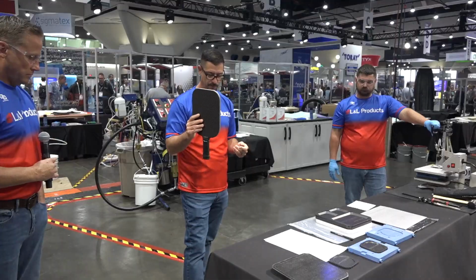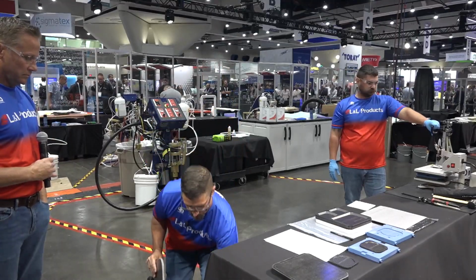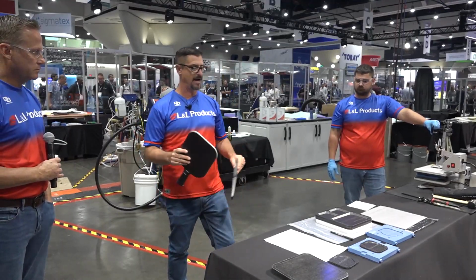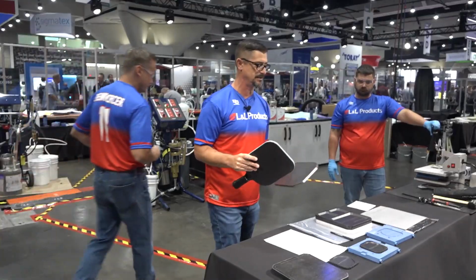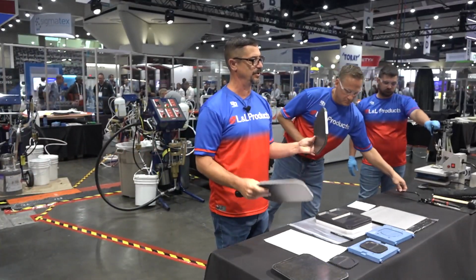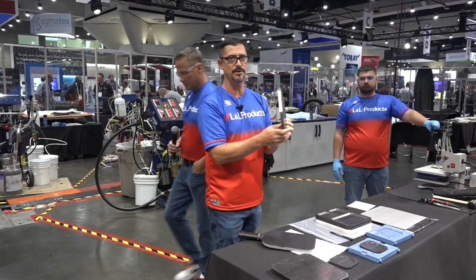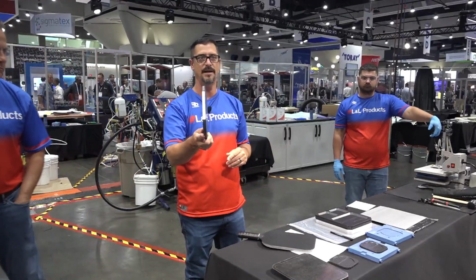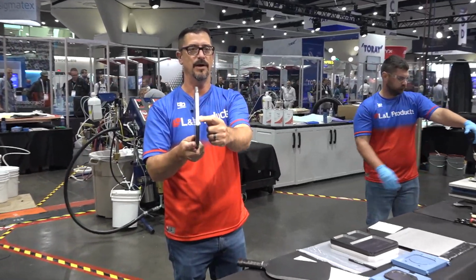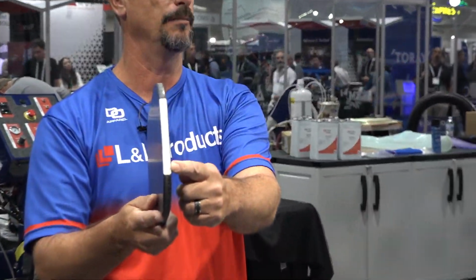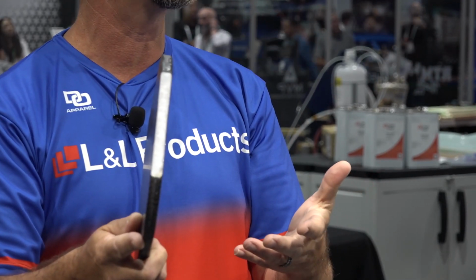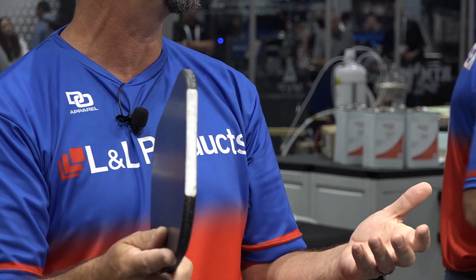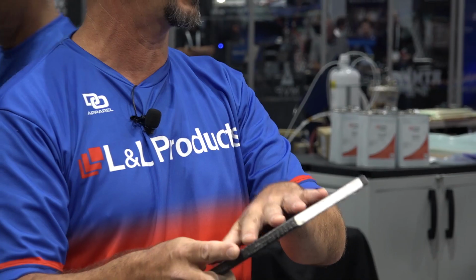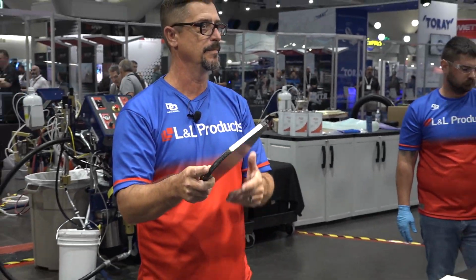We have both a thermoplastic and a thermoset version. I was looking in my box below because I had the thermoplastic one here yesterday, but this one will do. This one we just cut the handle off so that you can see the foam inside. It's a very, very closed cell structure. We've done water absorption tests on this material. We get 0% water absorption after 24 hours of submerging it in water.